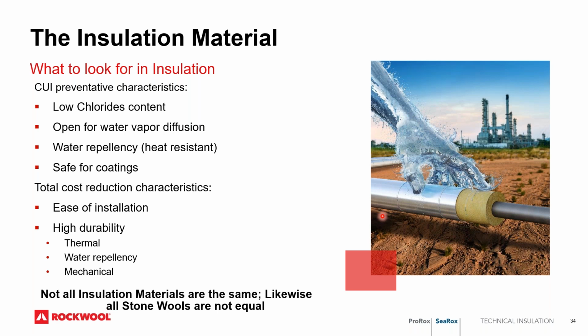So the takeaways are, okay, so what are our takeaways? Our takeaways are to look for low leachable chloride content, heat-resistant water repellency with an inorganic resin for low water absorption, and open for water vapor diffusion to allow for fast dryout times, and make sure the material is safe for coatings. A lot of the same CUI preventative characteristics translate to total cost reduction characteristics. The ease of installation has an effect on CUI in terms of proper installation.